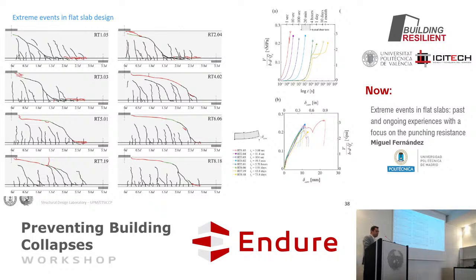So what was changing, in fact, was not the material properties. The changes in the strength that were observed were basically due to the difference in the shape of the crack, in the kinematics of the crack. But we saw very consistent results to Sarah, by the way, because we were not capable of breaking any of the beams in long term, and so we needed to reload them, as you were doing also, in order to reach failure.